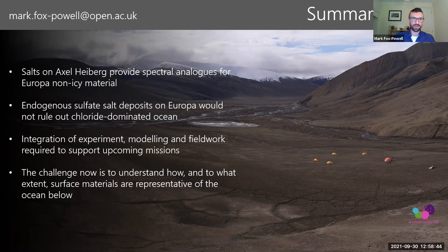Certainly sulfur from Io does end up on Europa, and it is a major contributor to the composition of Europa's surface. And the question really is, to what extent is that material recycled down into the ocean? To what extent are the sulfates that we see on Europa purely from Io? Are some of them endogenous? Are some of them native Europa sulfates? Are they all from Io? So these are ongoing questions. It certainly seems that the youngest regions of Europa's surface are quite sulfate poor, especially the ones that are away from the peak of Io's sulfur bombardment.